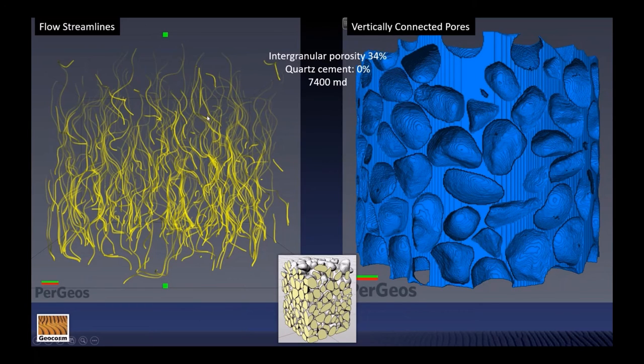Now the spaghetti over here on the left is the result of a flow simulation where we're flowing fluids from the bottom of our pore space to the top. And so you can see that the spaghetti in this case is nearly vertical, and that's because we have very low flow path tortuosity. These are the streamlines from our flow simulation. So when we have no quartz cement here, we're getting about 7 darcies permeability. Let's see what happens to the pore space, the tortuosity, and the permeability as we progressively fill in these pores